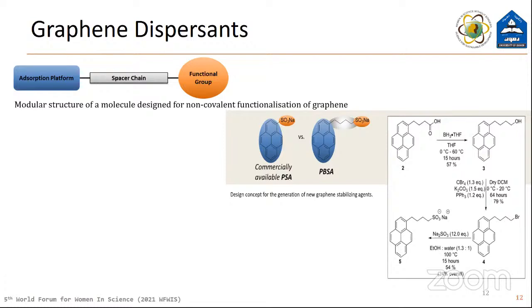PSA is effective at producing aqueous graphene dispersion of up to 0.7 milligram per milliliter, but its structure is likely to be far from ideal for this function. Based on a group study, they observed that the pyrene derivatives with a sulfonyl group yield higher graphene concentration than their carboxylic acid analogs, and also that 1-pyrene butyric acid outperformed 1-pyrene carboxylic acid. Therefore, it was hypothesized that the insertion of an alkyl chain between the adsorption platform pyrene and the functional group SO3Na, which is the sulfonic group, would improve the efficacy of the dispersants.